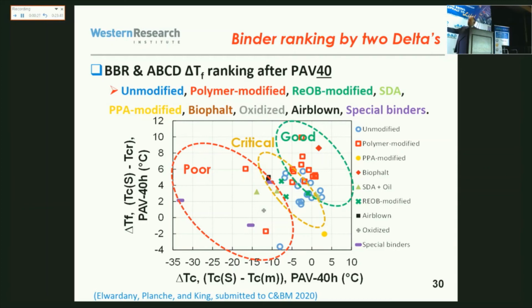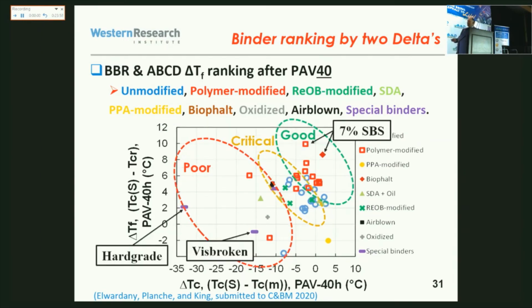So those, they have a very good delta TC. We don't need to worry about them. And we don't even have to measure the delta TF. For those which are very, very bad in delta TC, we don't need to measure delta TF. The question is those which are critical. So if we look at them in more detail, the 7% SBS modified, they are all up here. That's where we expect them to be. And then here we have a visbroken residue. Here we have a hard grade, the ones which are bad.